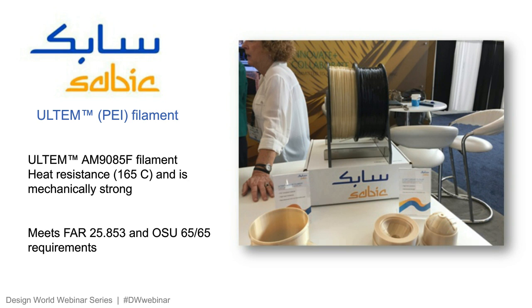AM9085F filament is a high-performance polyetherimide product manufactured from Ultem 9085 resin. It offers heat resistance to 165 C and mechanical strength. It is UL94 V0 compliant at 1.5 and 3.0 millimeters and meets FAR 25.853 and OSU 65/65 requirements with low flame, smoke, and toxicity. It is available in black and non-pigmented colors.